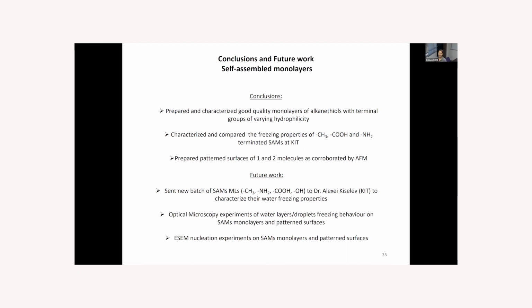In the future, we already sent the new batches of SAM monolayers to Dr. Alexei Kiselev's lab. This time of 4 molecules: the methyl group, amino group, carboxyl group and hydroxyl group terminated surfaces, to characterize the water freezing properties. And we would like to do the optical microscopy experiments with layers of water and see the behavior of these monolayers on water freezing. And we will also do the environmental scanning electron microscopy nucleation experiments and see if we can see any differences or any interesting behavior.